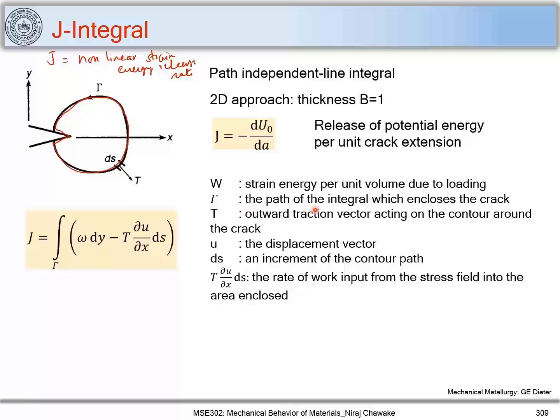So this is the path of the integral which encloses the crack. This is a T, which is nothing but a traction vector, that is a force acting on this crack on this path, small path ds, which is nothing but an increment of the contour path. So when we consider this small path and we try to integrate for a whole path of gamma, and this